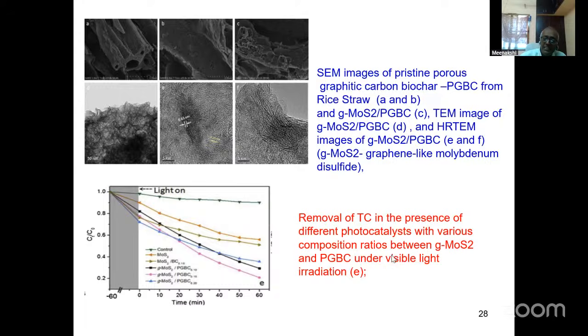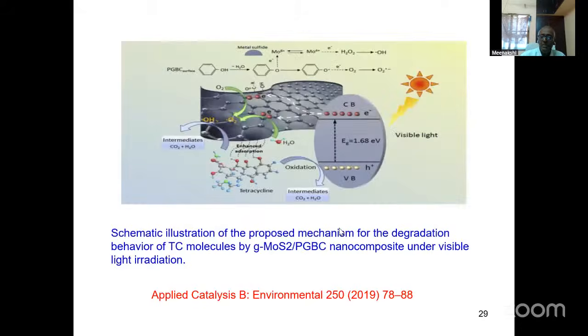Here they have tested the degradation of tetracycline. TC is tetracycline. This is the removal of tetracycline in the presence of different photocatalysts. You can see that this one, graphene-like molybdenum sulfide with PGBC, is found to be most efficient in degrading the tetracycline. This is the mechanism proposed for this one. As I told you earlier, the biochar is acting as an electron sink. So the electron is removed from the conduction band of molybdenum sulfide and given to oxygen, forming superoxide radicals, and the holes are available for the oxidation of tetracycline.